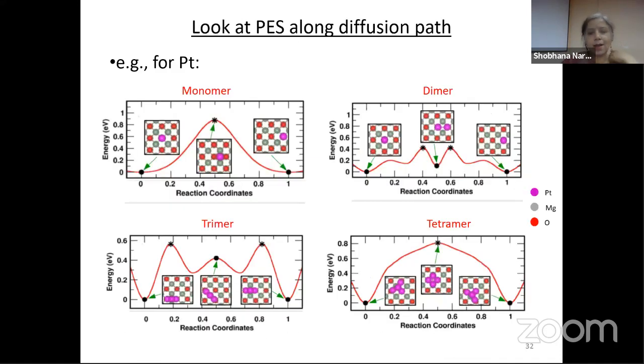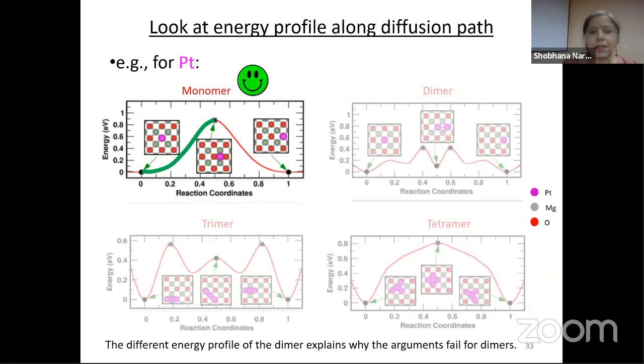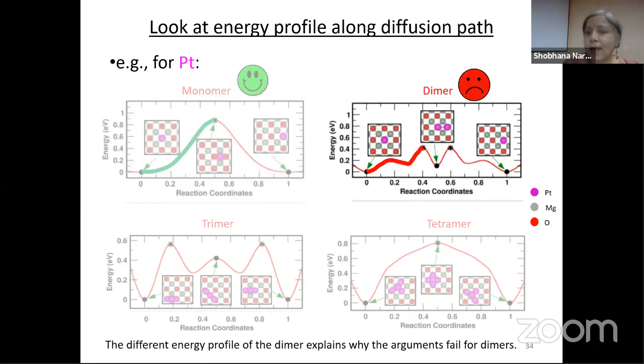So let's look at our energy landscapes for the diffusions for platinum as an example. For the monomer, it was approximately parabolic. So that's fine, and we got the correlation. For the dimer, it is not parabolic, notice it, because you have this extra minimum. And we did not get the correlation.